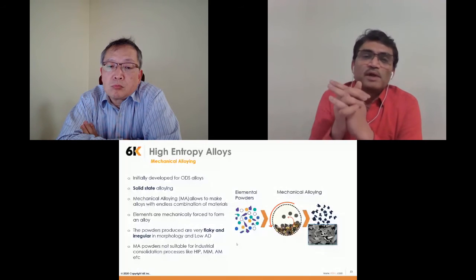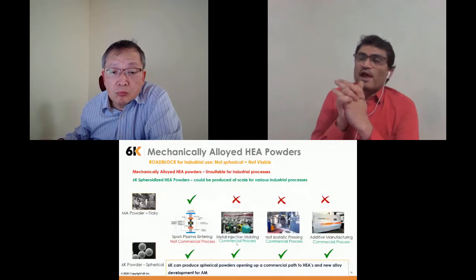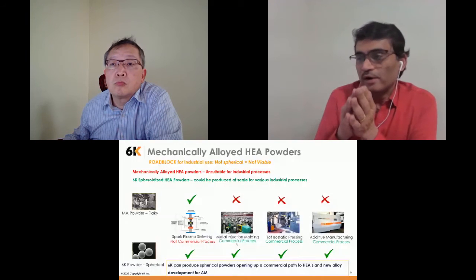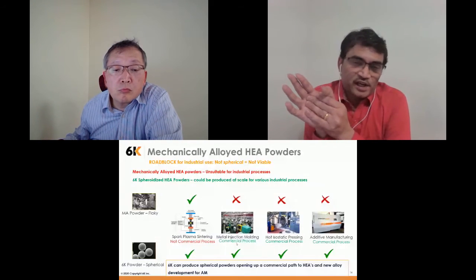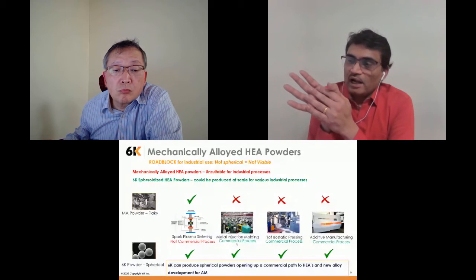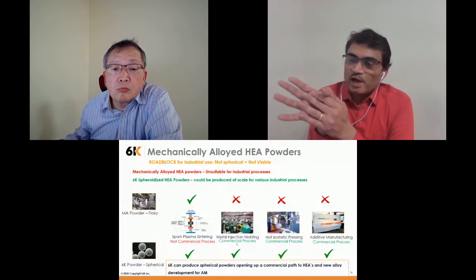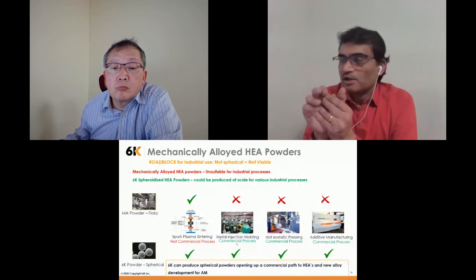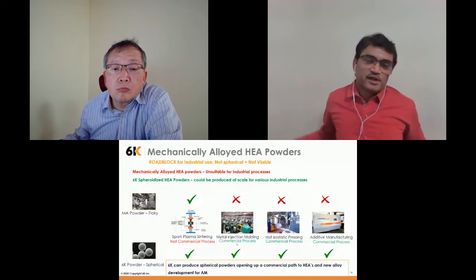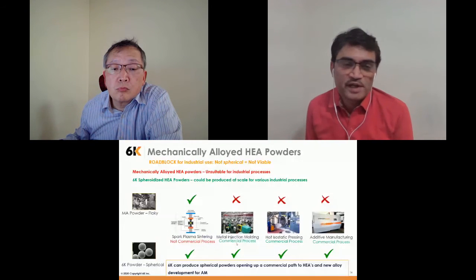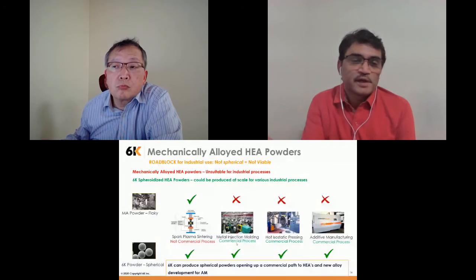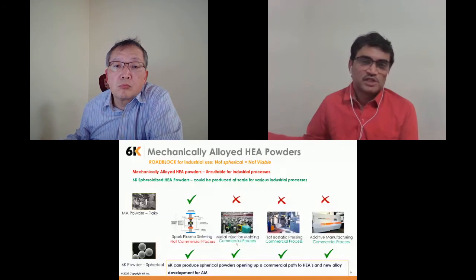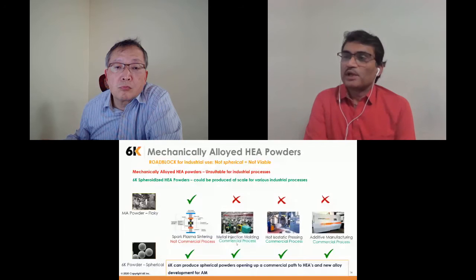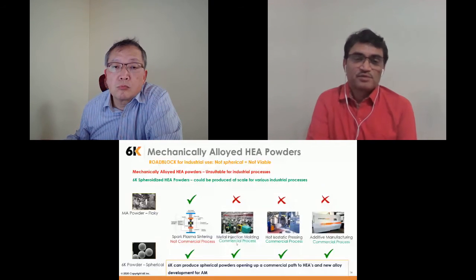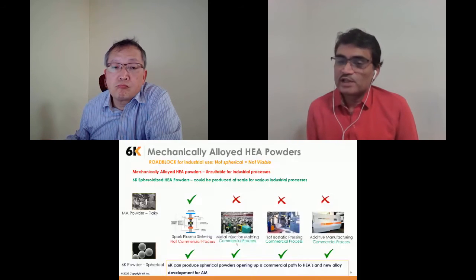So basically what happens here is when you produce mechanically alloyed powder, it can be used in spark plasma sintering, and that's what people are using for research. And spark plasma sintering is not an industrial process. This powder cannot be used for other industrial processes like MIM, HIP, or additive manufacturing. But as soon as you have this powder in spherical form, it can be used for different industrial or commercialized processes that we know of today. And that's what 6K brings, this value to have these kinds of alloys in mainstream application at scale.